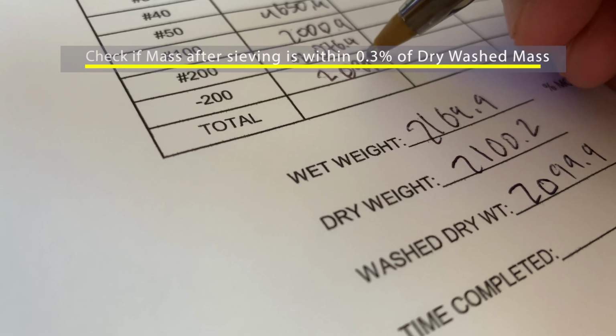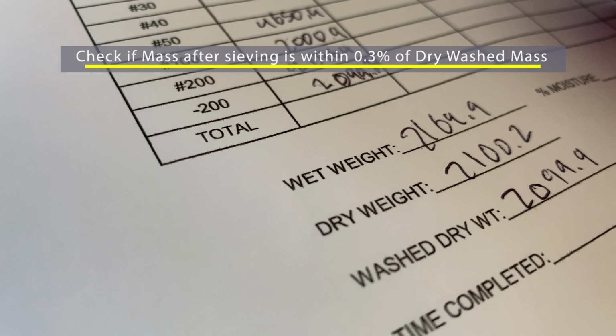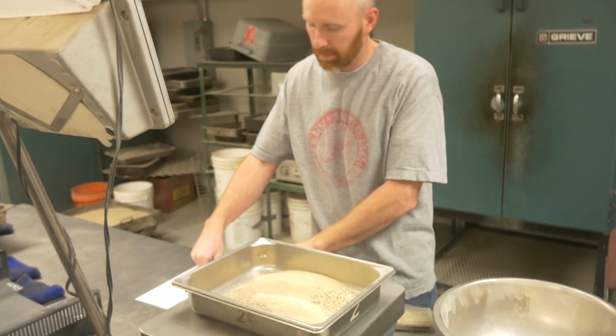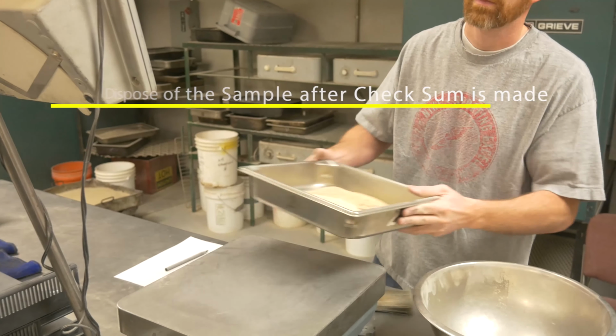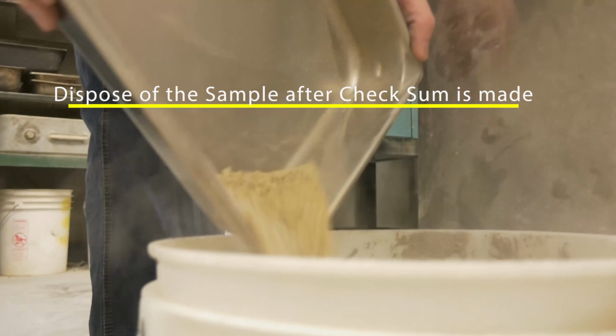Check if the mass after sieving is within 0.3% of the dry wash mass. This is called a checksum. Dispose of the sample after the checksum is made.